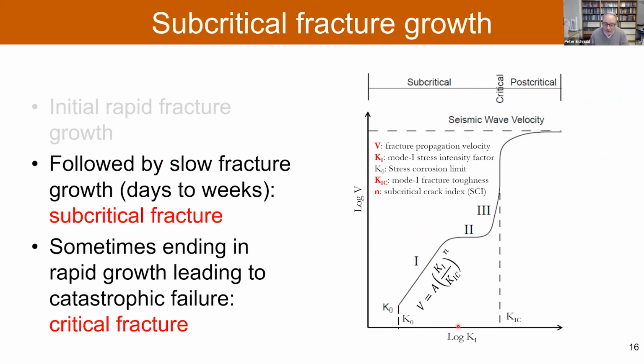And this is a plot of the stress that's applied to the fracture, the loading stress, and the velocity of the fracture propagating, but it's in log space. So in linear space, this curve would be curving up, but now it's shown as a straight line. That's the slow growth accelerating over time. So it starts here, then it gets faster and faster, but still slow. Then there may be a phase of constant velocity, and then all of a sudden it gets really fast. So the vertical part there would be instantaneous, right? Because the velocity goes up to the seismic wave velocity. The seismic wave velocity would be the upper limit. So this is called subcritical fracture growth.